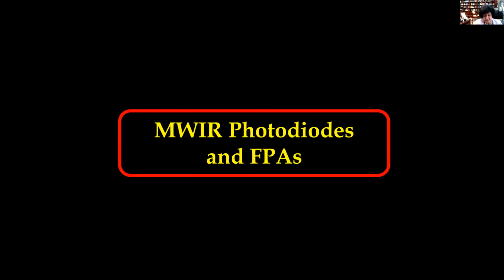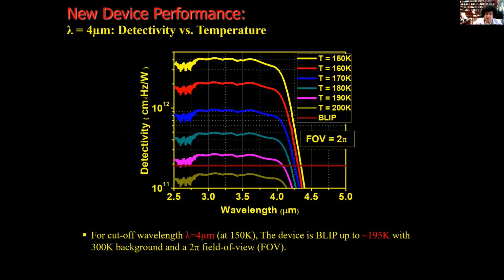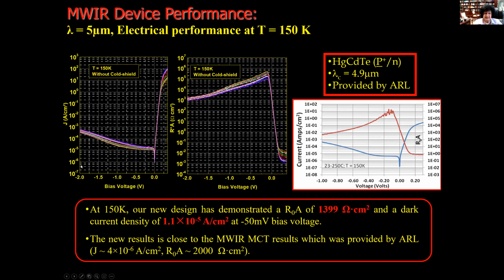Now, coming to the mid wavelength again, 3 to 5 micron, and comparing again with mercury cadmium telluride, which is 60-70 years old technology. We can see here detectivity as a function of wavelength for different temperatures, and the BLIP temperature here is about 195, with the 300K background and the 2 pi field of view, and that is equivalent to the best. Again, as we can see here, that's the dark current and the R0A, and it is the best comparing apple to apple with mercury cadmium telluride, to show that yes, this material can compete with the best of mercury cadmium telluride with a much thinner, much cheaper, and much simpler structure.